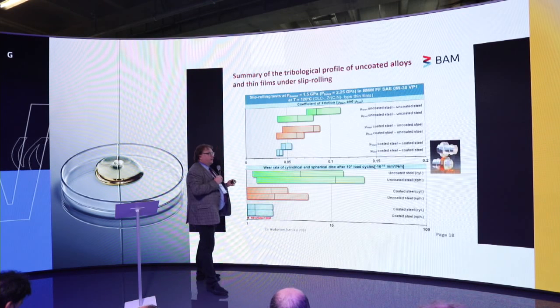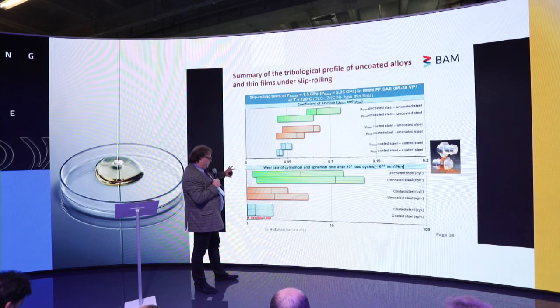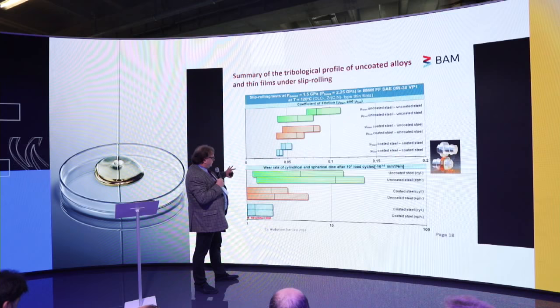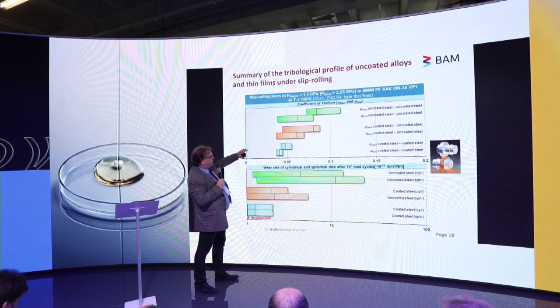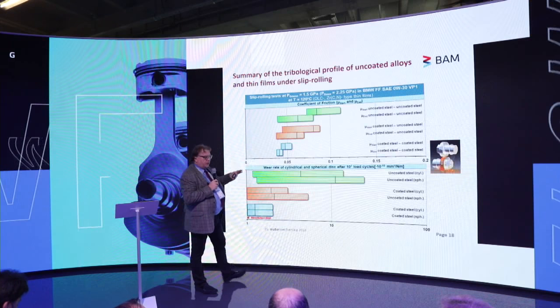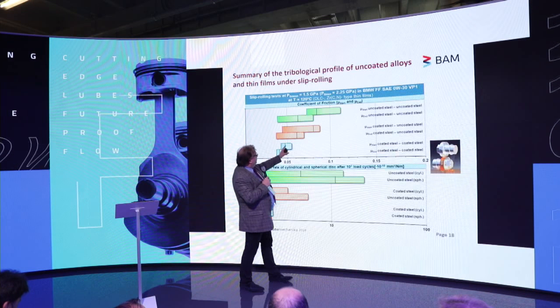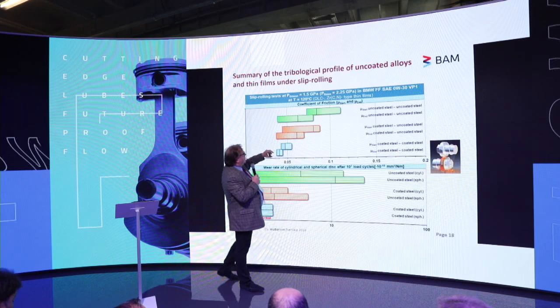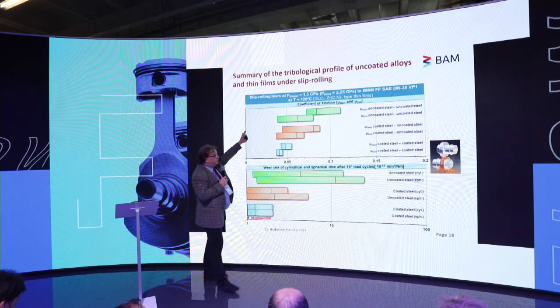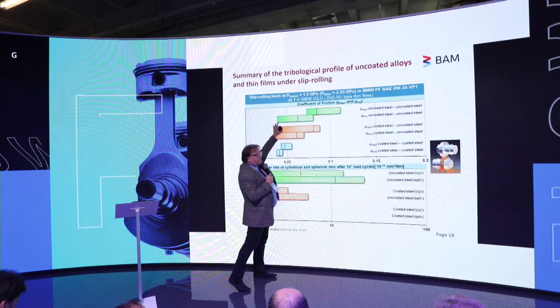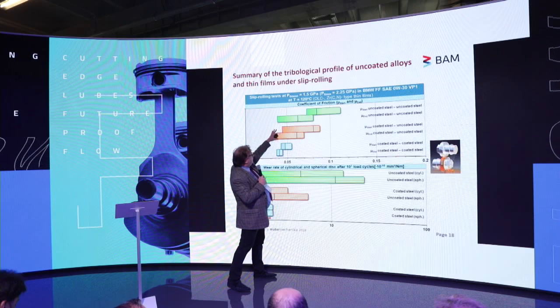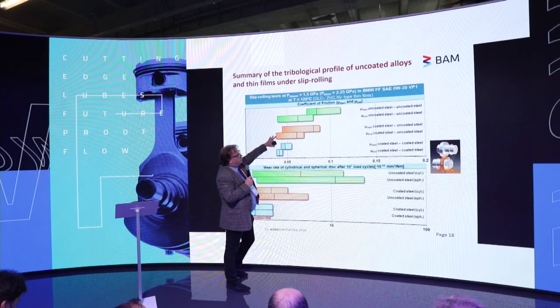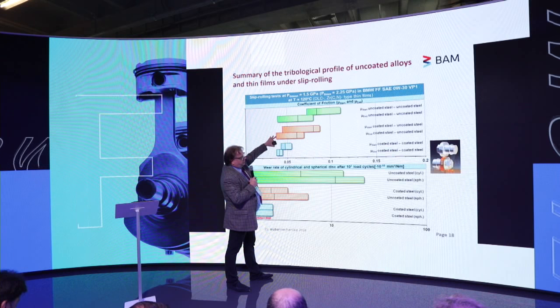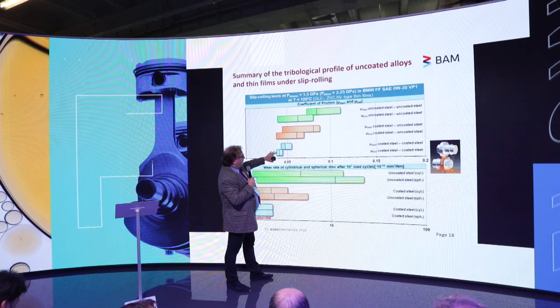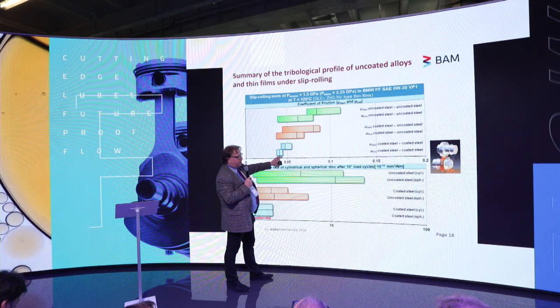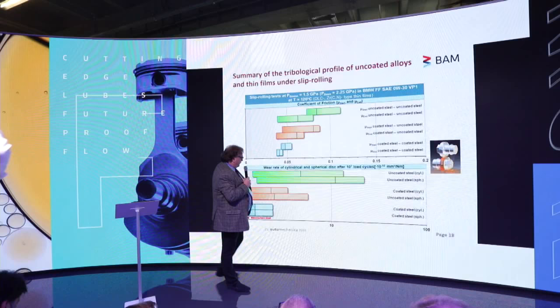In a management-friendly summary, if you put all together, here you have the wear rate, here you have the friction. If you compare all together, of course you have an average and you have a range. So it means when we start with uncoated steels, you can, if you have the right steel, go down in friction. But you can have the same effect with coating one part or with both. But you see, the safest is to have both coated because the range is the smallest.